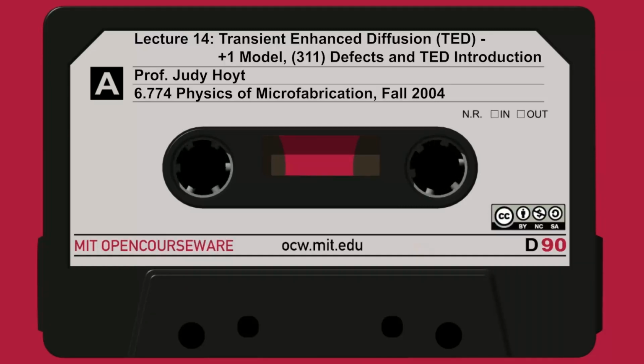This is a sample of silicon that's been implanted with an intermediate dose, 5 times 10 to the 13th boron per square centimeter, and annealed at 810, and this is after 5 seconds. You're looking in plan view, and each one of these little dot areas is a 311 defect. So there's a huge density of defects. The scale bar is a little hard to see in the upper left; from here to here is 40 nanometers, that's 400 angstroms.